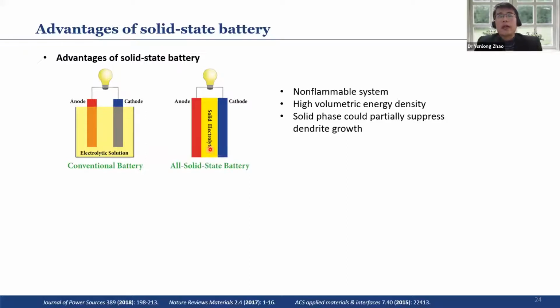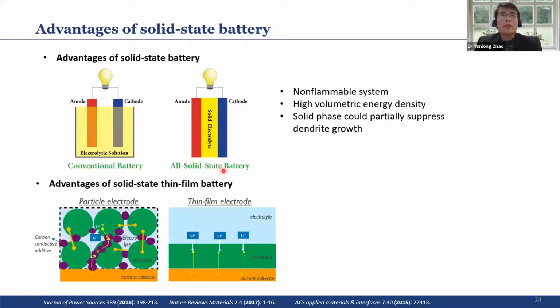And also, as I mentioned, the anode side can generate lithium dendrites, which can penetrate the separators. With solid electrolytes, initially people thought they could fully suppress the dendrites, but after some recent studies, they found they can only partially suppress them, so this is still a problem. By the way, when I talk about this kind of battery, I am introducing particle electrodes. I mean the anode or cathode materials are large particles, which are assembled into the electrode and then into the batteries.